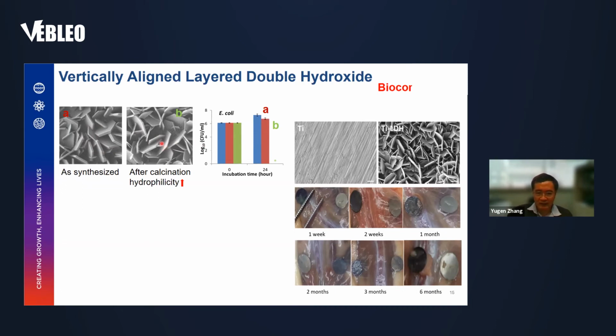And when we look at the antimicrobial properties, showing here against E. coli, you can see the as-synthesized one actually did not show much killing, but after calcination, it has great antimicrobial properties. And then we grew this structure on titanium, a widely used implant material. And you can see after calcination here, we make this titanium disc. And this is a non-coated and this is a coated one.